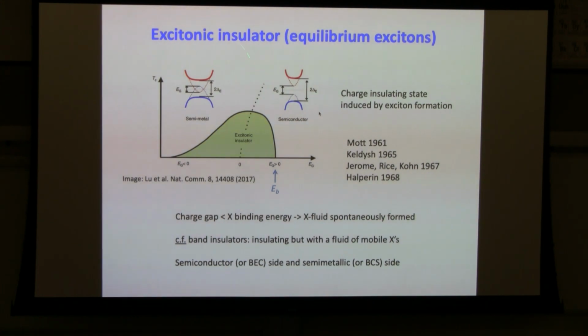Okay. For this reason, let me first introduce the concept of an excitonic insulator, which, as far as I know, was first proposed by Mott in 1961, and the theory was further extended by Keldysh, Jerome, Rice, and Kohn, as well as Halperin in the following years. So imagine now you have a semiconducting material with a tunable band gap, e.g. here, this is the axis that you can tune the band gap. And if you can tune the band gap of the semiconductor to be smaller than the binding energy of the exciton, then the system actually can gain energy by spontaneously populating a fluid of excitons once you reach this condition here. So once you go below the binding energy, you can populate a spontaneous fluid of excitons.